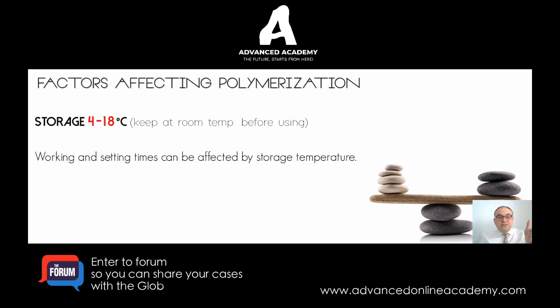Self-adhesive cements are stored between 4 to 18 degrees Celsius. Keep that in mind. They're not like the conventional resins, which I said were 18 to 22. At 4 to 18, they have to be refrigerated, and that will affect the working time and will affect how long you have to cement multiple crowns if you're doing so. Please store them very carefully.